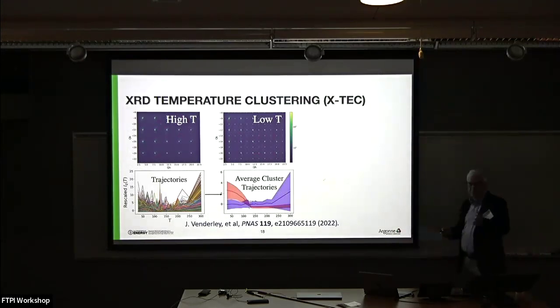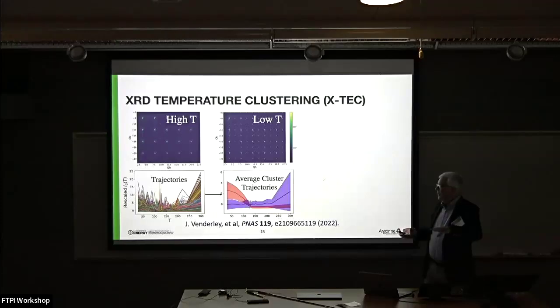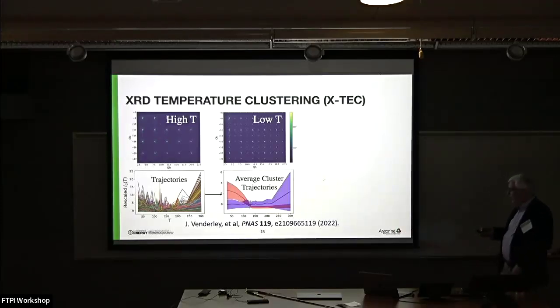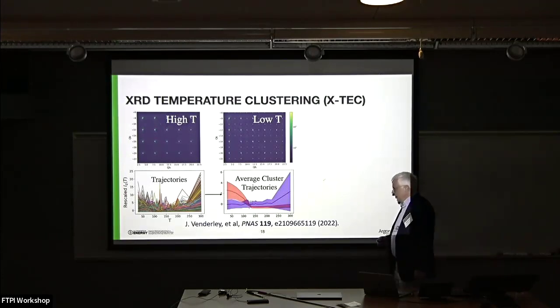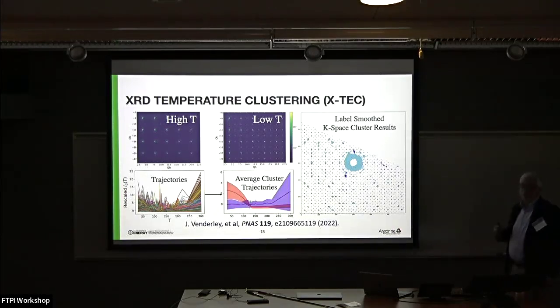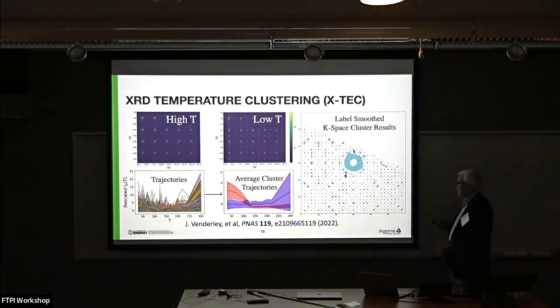And that means that if you look at the trajectory of every single voxel, and we're not just taking the superlattice peaks, we're taking everything, and then try and cluster them, well, in a simple two-component cluster, once you threshold out all the background, which is not doing anything interesting with temperature, you can end up with essentially two components. We have those peaks which show no interesting temperature dependence, and those which are turning on at the transition. Furthermore, it can tell you exactly where those voxels are that are turning on. So without having to do any training about crystallography or something, the unsupervised machine learning has identified that all these superlattice peaks are occurring, for instance, at these half-integral positions, and they're color-coded now. So this becomes like a kind of map, a Google map or something, where green represents forest reserves and blue represents the factory districts.